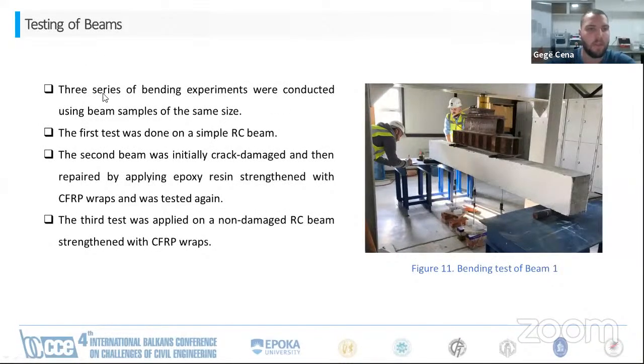Testing of beams. Three series of bending experiments were conducted using beam samples of the same size. The first test was done on a simple reinforced concrete beam. The second beam was initially cracked and then repaired by applying epoxy resin and strengthened with CFRP wraps, and was tested again. The third test was applied on a non-damaged reinforced concrete beam, but just strengthened with carbon fiber reinforced polymer